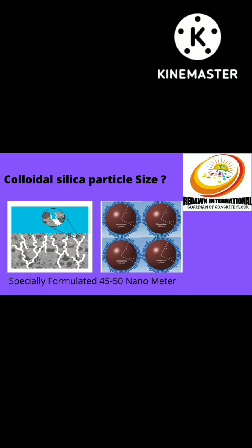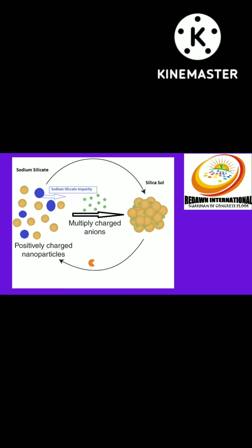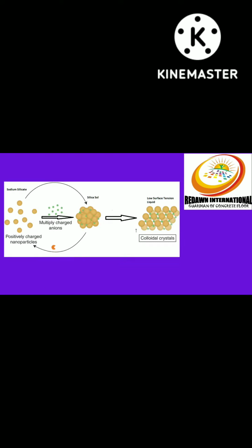Colloidal silica sol cannot be made simply by mixing silica into water, as sodium silicate is. The high-tech industrial process begins by stripping sodium and a considerable portion of contaminants from sodium silicate and then suspending the purified silica in a low-surface tension liquid. The term colloidal silica sol always refers to a liquid material.